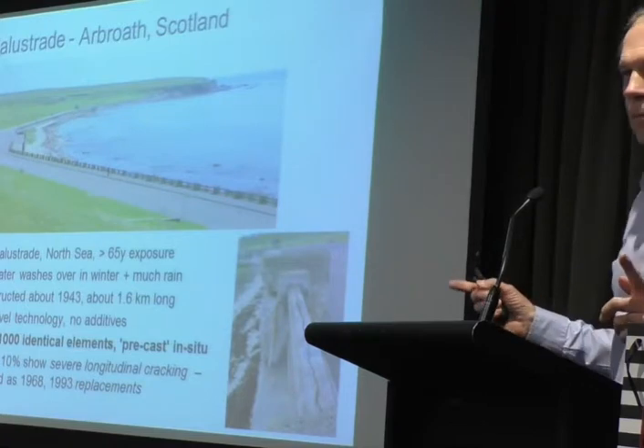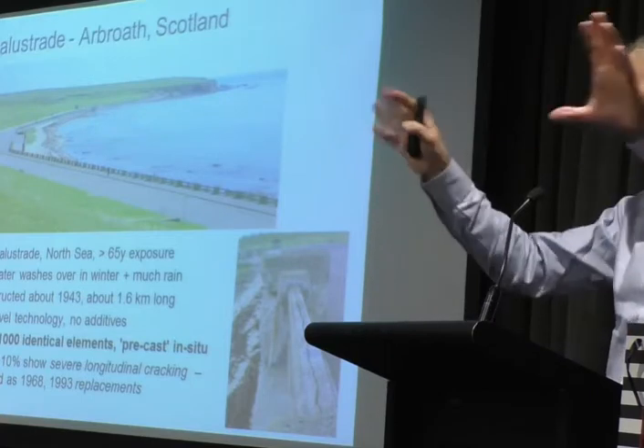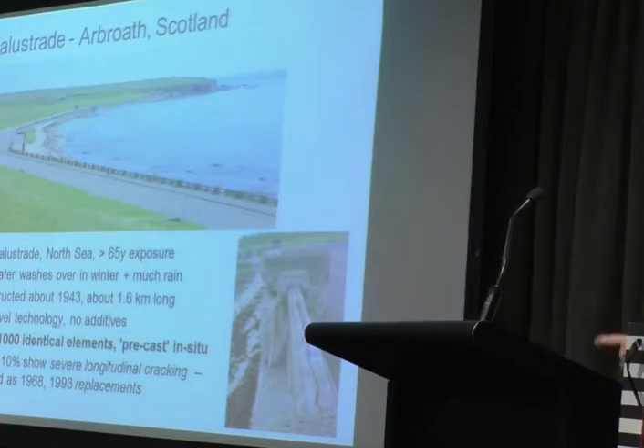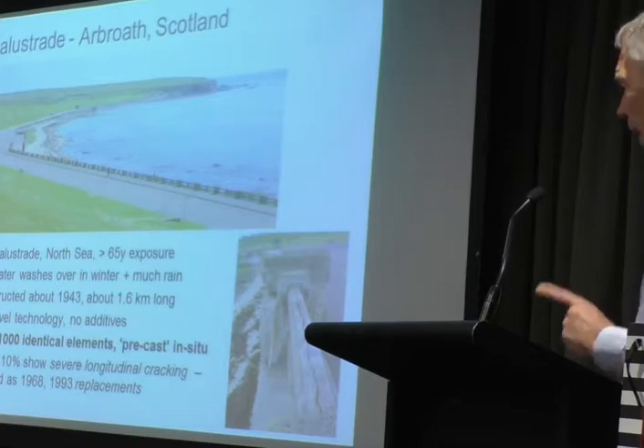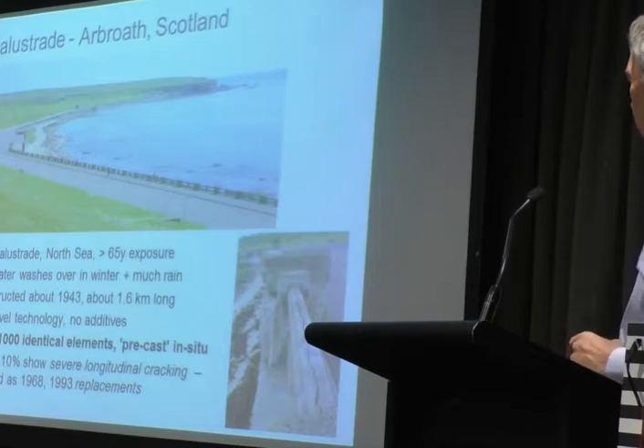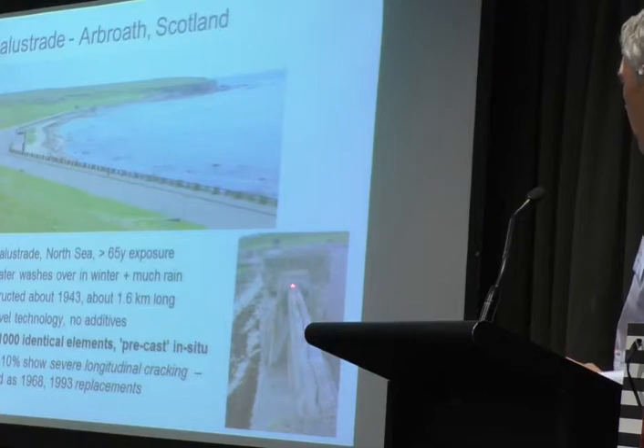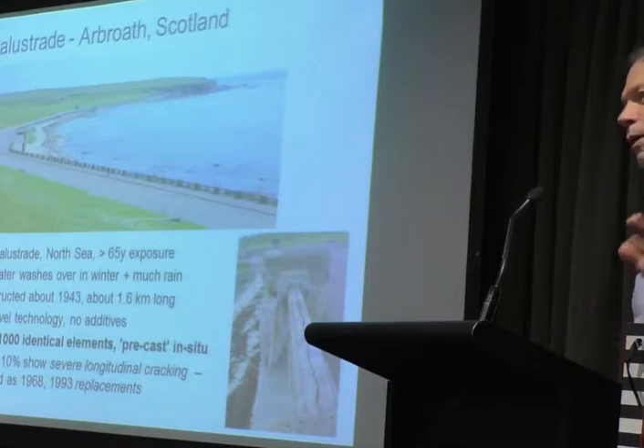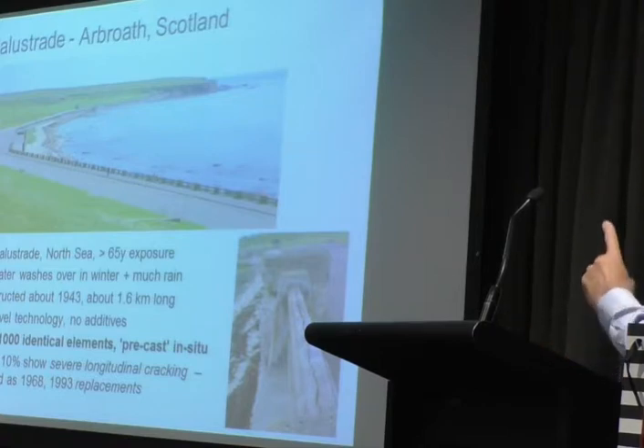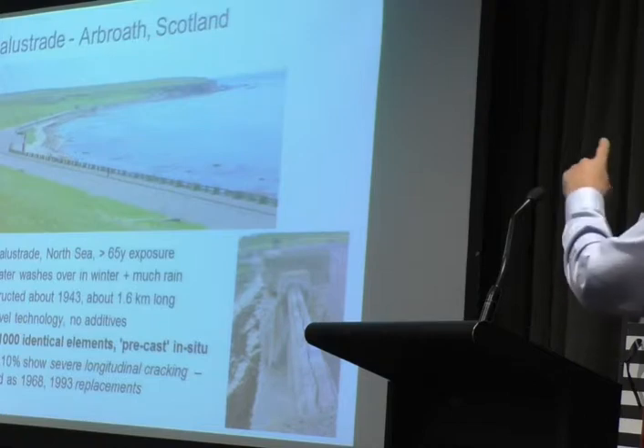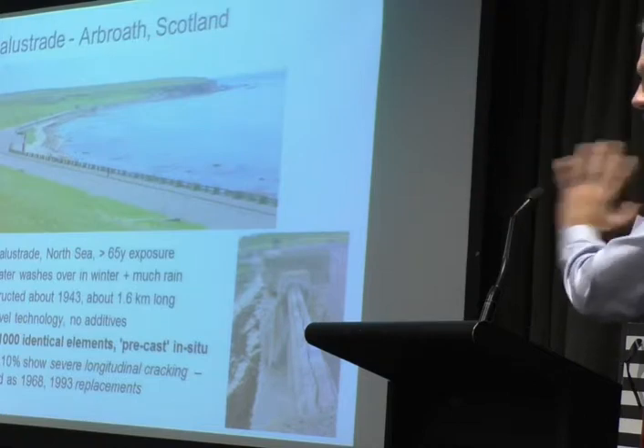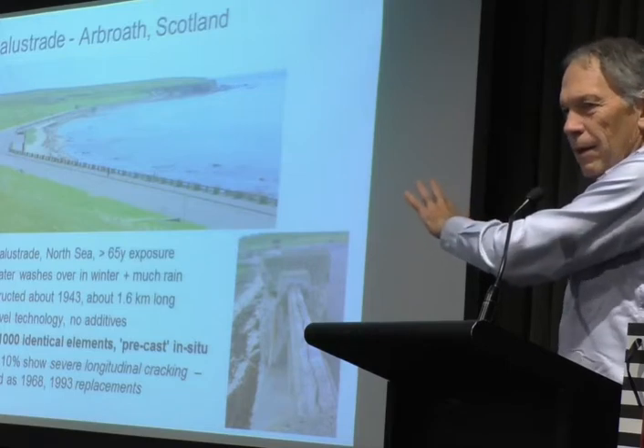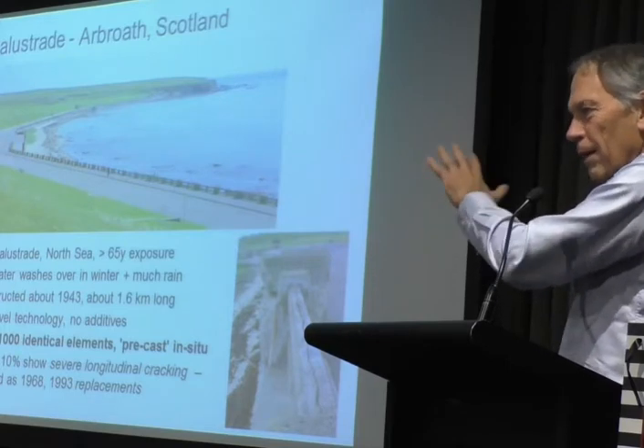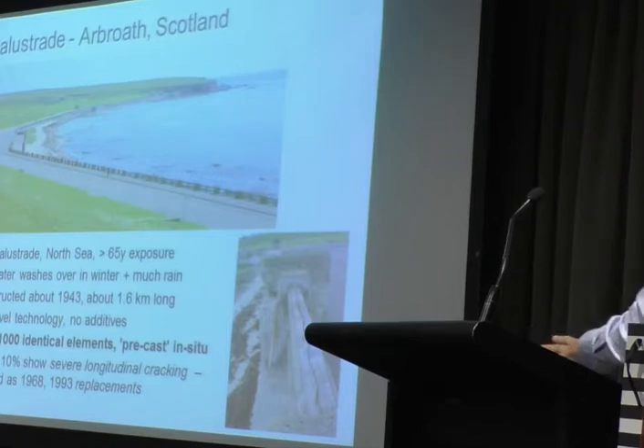They were all precast because the verticals were cast later and you can actually see it from the construction. But there's nearly 1,000 of these. Now out of that 1,000, we discovered that some of them had cracked really, really badly. And that was about 10% of the whole lot. But when we inspected the concrete and talked to the local council and so on, we found that these were replacements for the 1943 ones. So 90% of the 1943 ones were still there. It's the ones that had failed that were built later as replacements.